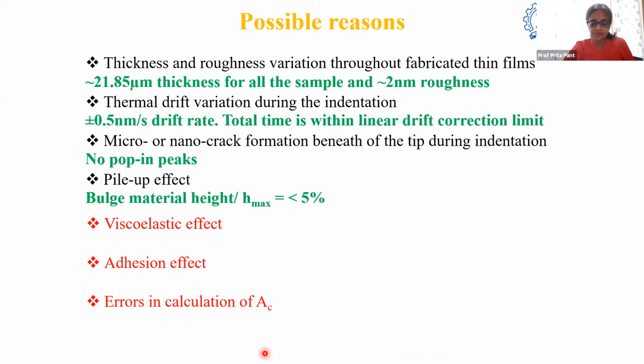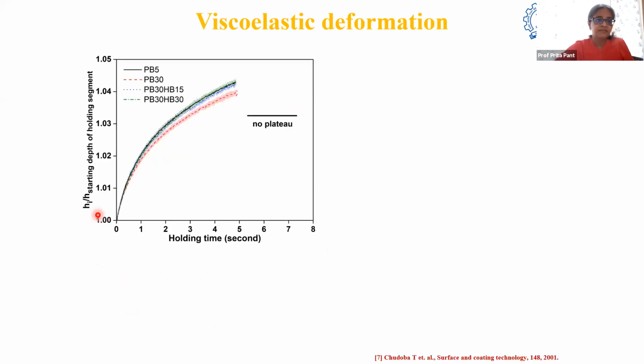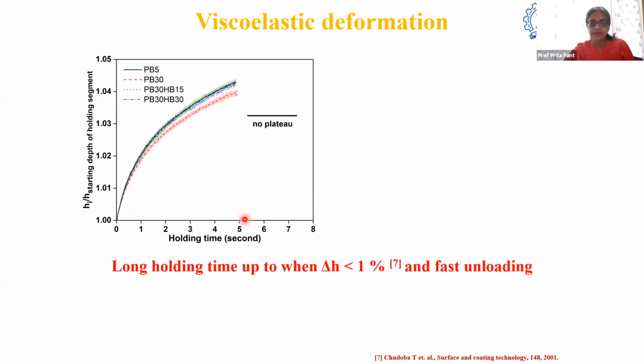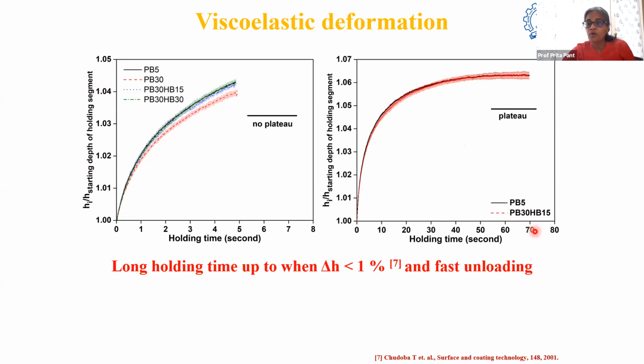So viscoelasticity first, that's the easiest to deal with. This is the starting H instantaneous versus the starting depth at the beginning of the hold segment, right? So this is that holding segment that I gave. And you can see that displacement is still increasing, right? So a 4-second hold, a 5-second hold doesn't do it for me. But if I give a long holding time here, if I hold it for about 70 seconds, you can see that this has plateaued out, right? So if I give a long enough holding time and then unload, then I hope to have gotten rid of effects of viscoelastic deformation, confounding my unloading results.